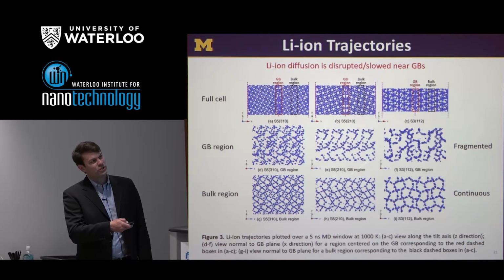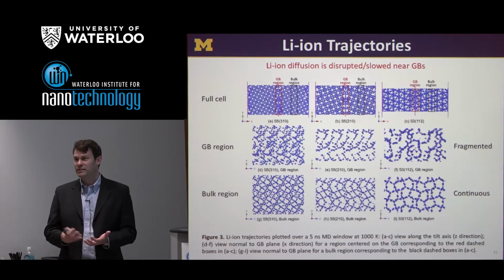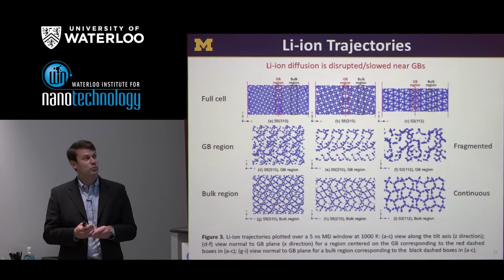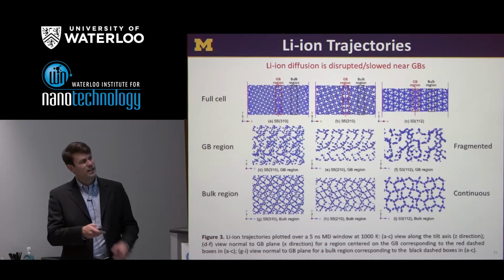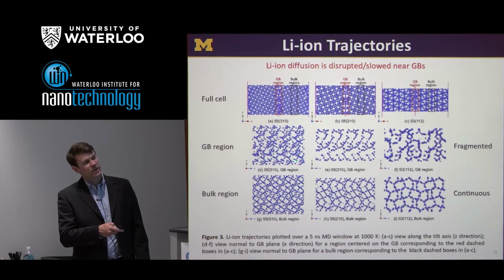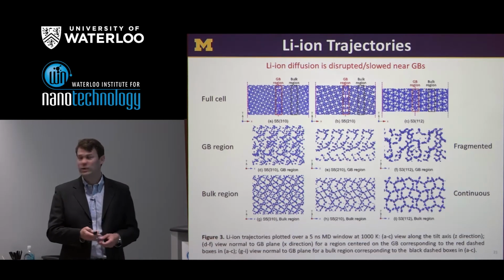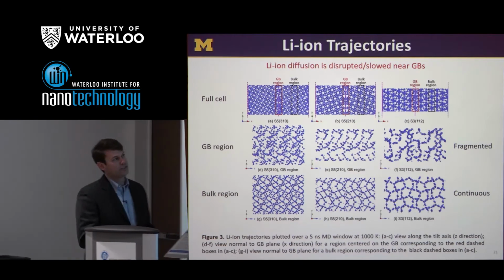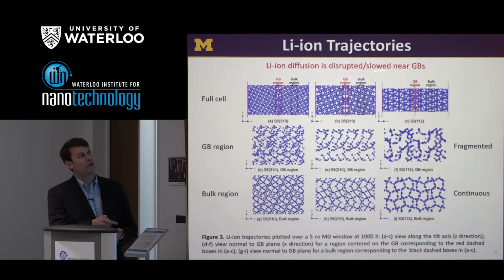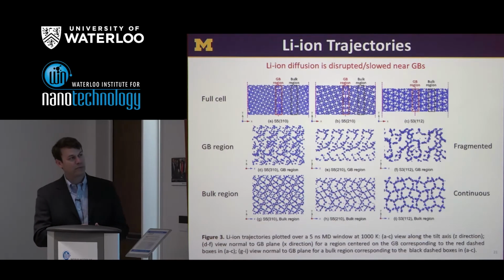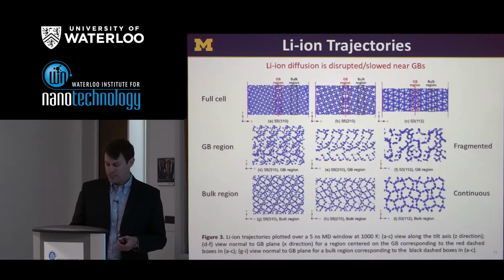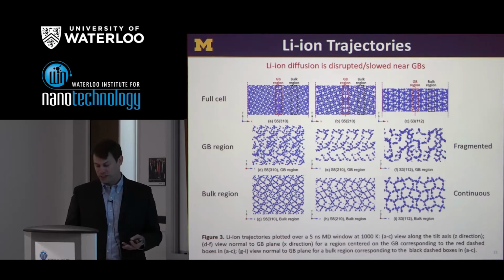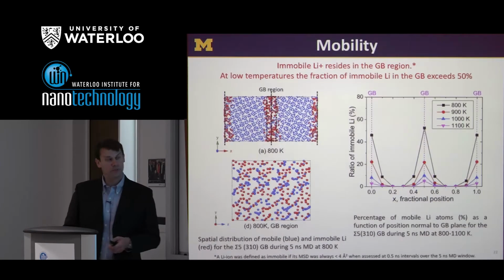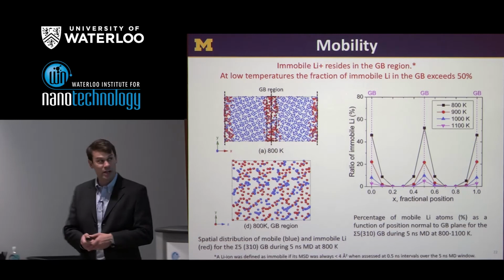Let's first look at the bulk. So looking at the bulk region, we see a trajectory which is relatively well connected. Lithium can percolate and move rather freely through the bulk region. But then comparing that to what's happening in the grain boundary, you'll see that these trajectories are now more fragmented. There's basically gaps between the lithium locations, which is indicative of a slowed or disrupted diffusion in the grain boundary plane. So again, this qualitative picture shows us roughly speaking what's happening with respect to mobility in the grain boundary region.